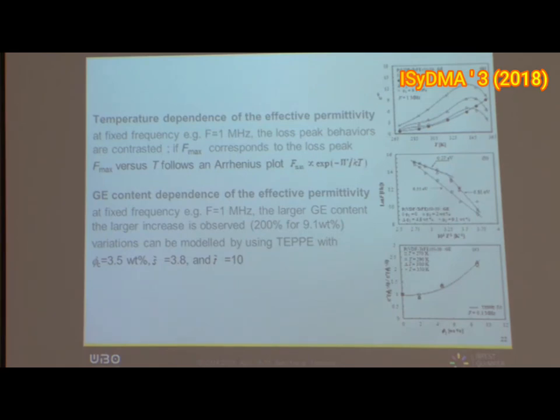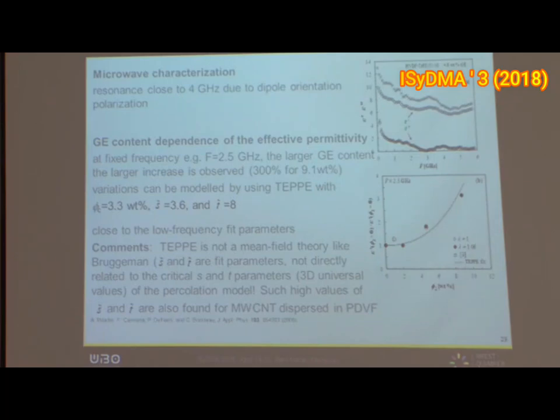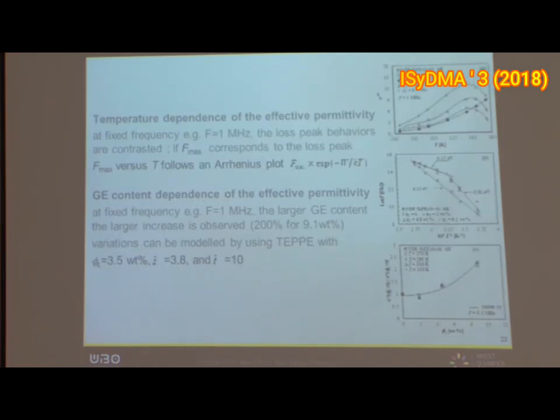What is much more important is to look at the dependence of permittivity versus graphene content. It can be very well fitted with the TEPPE model, otherwise stated as a McLachlan equation, with a set of parameters: percolation threshold and two exponents, S and T. These are results at low frequency.